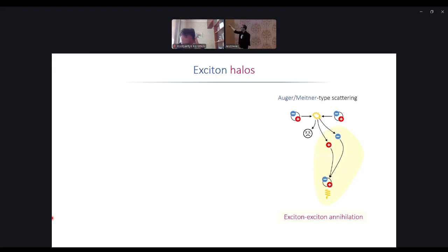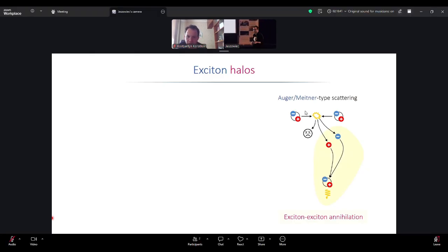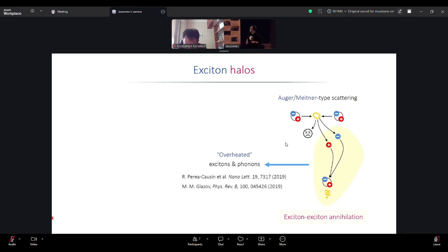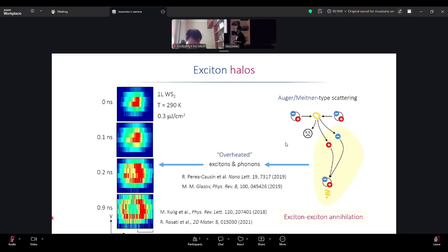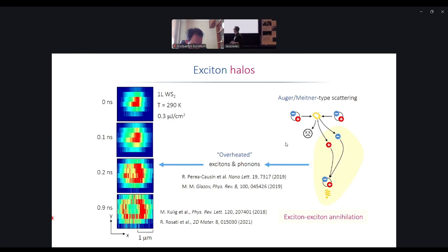What also can happen is that these excitons that are created have excess energy. You have additional phonon wind or drag, so you have expansion of, for example, phonons or even hot excitons from the middle of the spot. And if this effect is strong enough, it will lead to something quite unusual and occasionally observed also in quantum wells for gallium arsenide, but also here, that the shape, this Gaussian shape of the exciton distribution can even morph into a ring because the excitons are pushed out from the middle. Yeah, this is a more extreme case of exciton-exciton interaction.